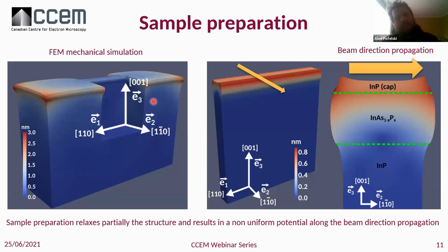So what is happening, coming back to our structure, is that since we have some free surfaces all around, the free surfaces will relax the strain on the edges, and the entire structure is going to undergo a certain deformation. You will see here the pillar regions undergo some deformation, some bowing. We are not interested in those pillar regions. We are interested in this window region in between. So this is then after a section of that from this. And you can notice that there is no deformation along this 110 direction, so no displacement in that case.